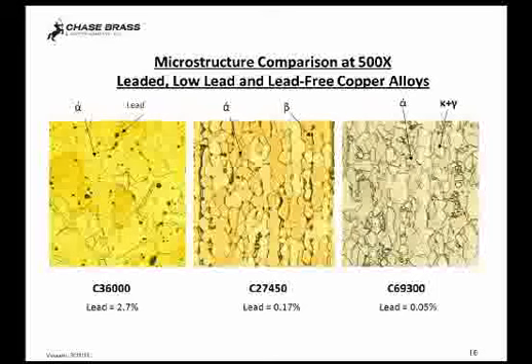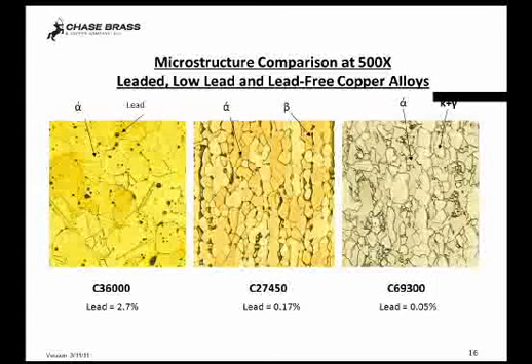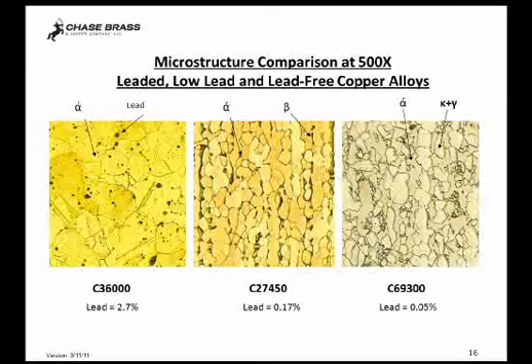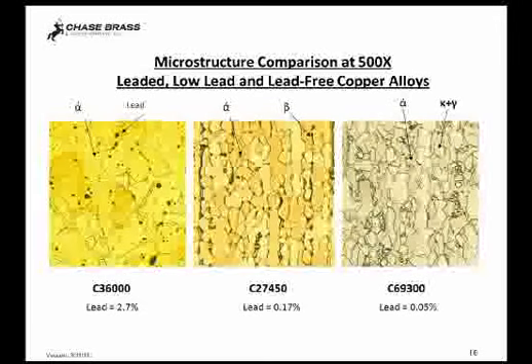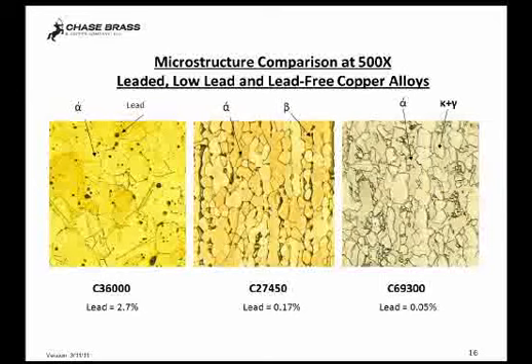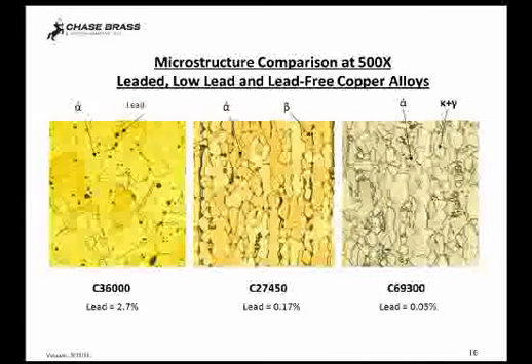Mainly, this alloy is a mixture of the uniform copper and zinc alpha phase, and then when you get above about 36% zinc, then you start to have zinc separate out in a high zinc phase called beta, and these particles here are beta phase. And then you get to some of the lead-free alloys, in this particular case 693 with 0.05% lead, there's no